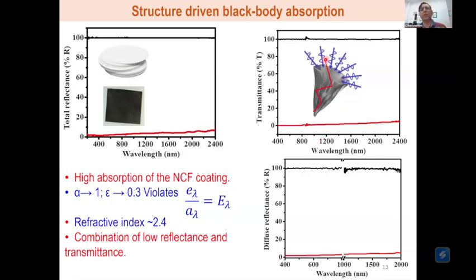And one of the reasons why it absorbs is because you have this cone, like I alluded to previously. You have this cone which is forming something close to a unit cell. And now if you put a photon in any direction inside a cone, it is only going to get internally consumed through a multiple internal reflection channel. It is going to get internally reflected and consumed and not come out. That means hardly any dissipation happens. The photon energy is completely thermalized and internally consumed by this material.